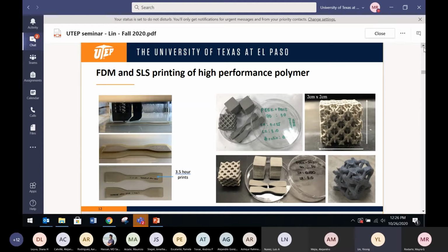The uniqueness here is that we're mixing this PEEK with PA12, which is nylon, because most sintering machines can only melt low temperature polymers because of power limitations. However, we are using PA12 as a binder to bind the PEEK powder together, and later, once you go through the sintering process, you will have a PEEK structure. As you can see, it's a lattice structurally designed and has lots of open pores, so it can be lightweight and carry a lot of mechanical loading. Next slide.